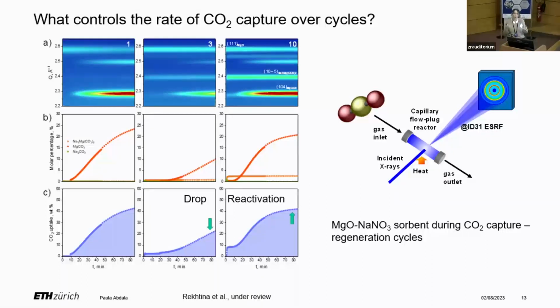How can we assess the structural parameters that govern the capture rate? As I mentioned, these materials operate in cycles. And we move here to a powder system, and we investigated this at the beamline with in situ time-resolved X-ray powder diffraction. What we observed already in the lab is that the CO2 uptake was not constant during cycling. So here are simply the diffraction patterns where we can observe the magnesium carbonate form. We took this large data set, did some parametric Rietveld refinement and quantified the phases at each point, which allows us to also fit this with a kinetic model.